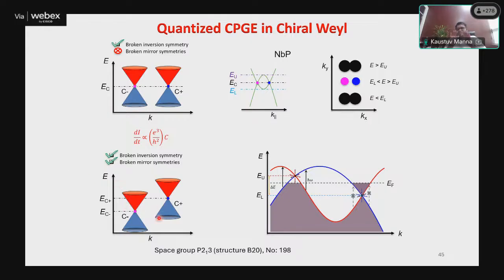You have to satisfy the shifting of this, right? The higher the shifting, the better the chance of getting the current, because the higher the energy range you get of the blocking part. When you do the experiment you need a decent energy, otherwise it will be in the background. So higher and higher separation gives a higher chance of getting current. Also this current is proportional to C, the Chern number. In nature, 99% of compounds have C equal to 1. It so happened that in the chiral crystal C is 4. Otherwise, you do not have any chance. That is the roadblock so far. We have been doping the compounds, manipulating the Fermi energy so that we can increase this energy window a little bit. But yes, it's very challenging.